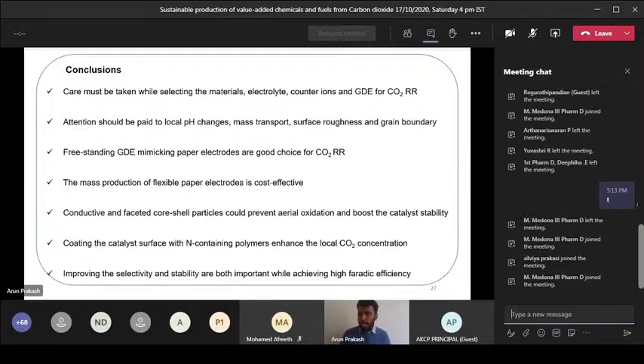If you use a carbon paper electrode or some paper electrode instead of a metal electrode, you are actually putting in less cost or low cost, so that also matters. And conductive and faceted core-shell particles. Instead of using a bulk metal, always go for nanomaterials like hollow structures, nano-sized material, micron-sized material, different phase shapes, high index, low index. You can tune that, and also core-shell structure.